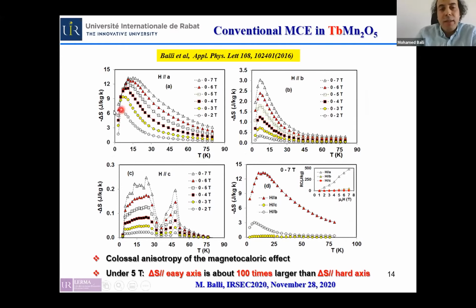Here is shown its entropy change along the easy axis corresponding to the A direction, the intermediate axis corresponding to the B direction, and the hard axis corresponding to the C direction. Similarly to the aluminum compound, this material also involves a giant magnetocaloric effect in the temperature range around 10 Kelvin. However, in contrast to the aluminum compound, the terbium manganese involves giant magnetocaloric effect at a relatively low magnetic field.